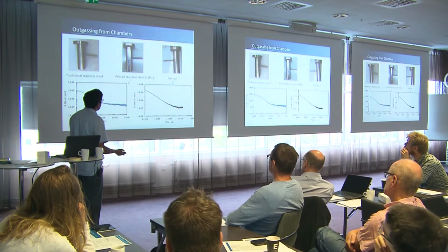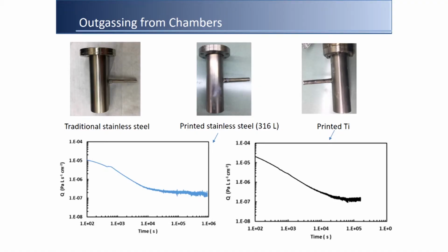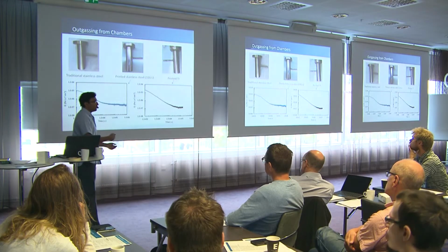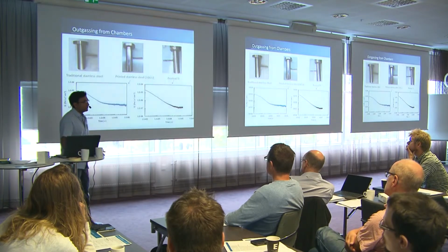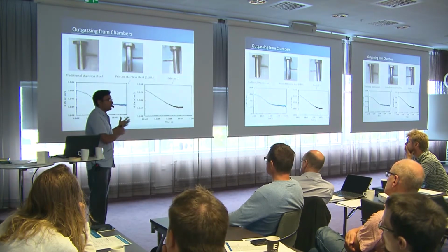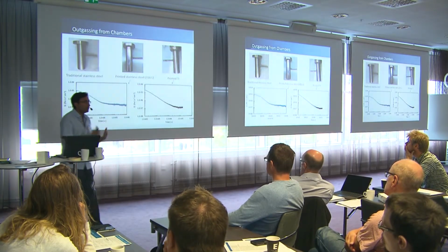So we then went ahead and had very simple chambers printed. These are test chambers, hollow cylinders, and these tubes here are welded on, and they are meant for a spinning rotor gauge experiment. So you can measure the outgassing rate and how much the pressure is building up as these chambers sit there. So far, what we can say is that the pumped on curves, just like you found, look very similar for both titanium and the 3D printed stainless steel. In fact, they're very similar to what's in the literature for normal stainless steel.